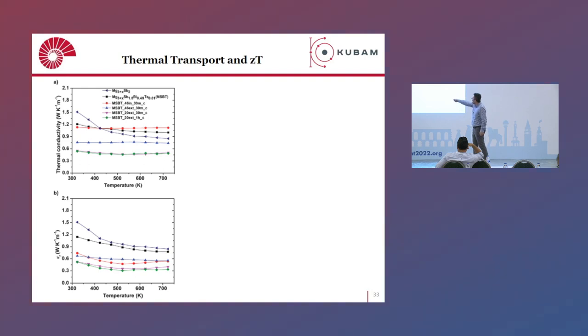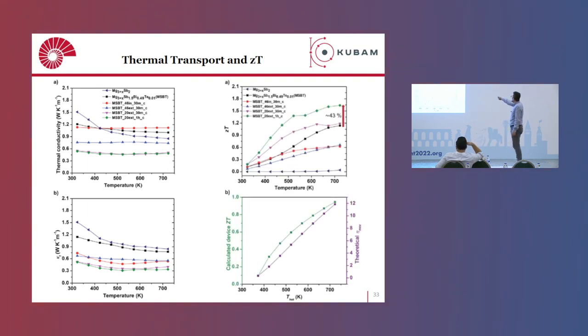But you can see that the thermal conductivity is substantially low. This is undoped. This is doped material around 1.2. When we do melt centrifugation, the total thermal conductivity is reduced by 50%, and the lattice thermal conductivity as well. So this overall leads to around 43% enhancement if you compare it with the MSBT phase. You can see it here. And if you calculate the device ZT, we can reach around 1 at this temperature, and the theoretical efficiency of this device would be around 12%.